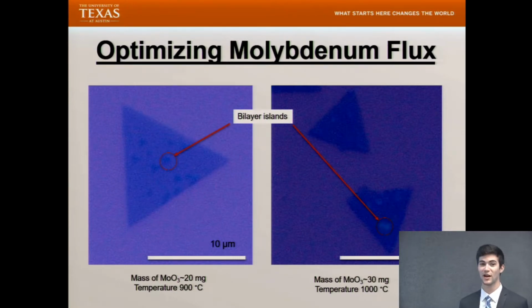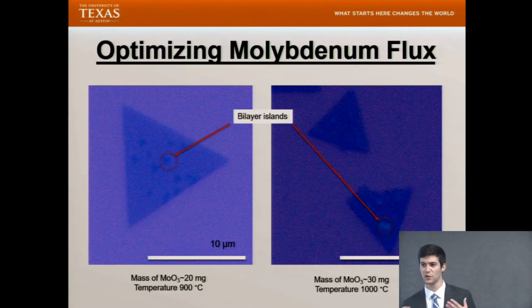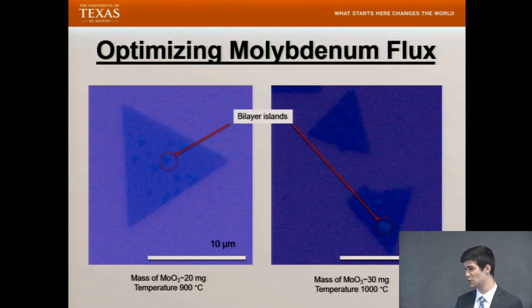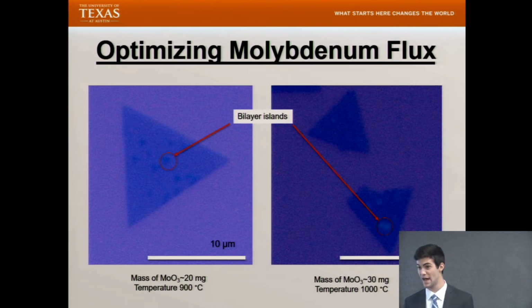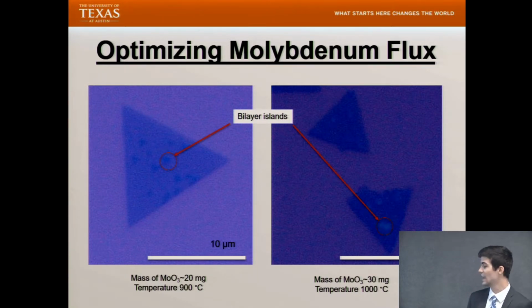The last parameter I optimized was the molybdenum flux. I found that if the flux was too low, only small domains would grow, if any at all. However, I found that increasing the flux led to these bilayer islands. So to avoid these bilayer islands, I had to find a balance between the growth temperature and the molybdenum oxide mass, which I determined to be 900 Celsius and approximately 20 milligrams of molybdenum oxide.